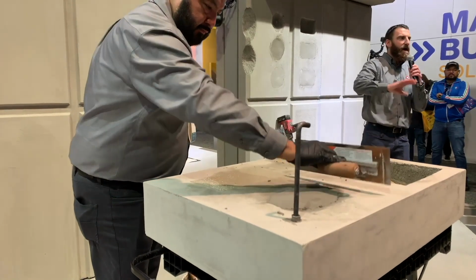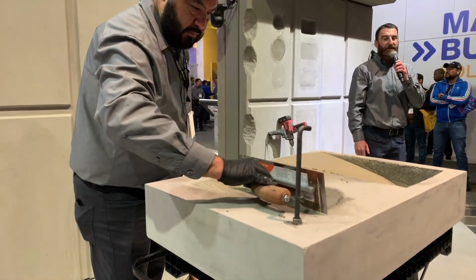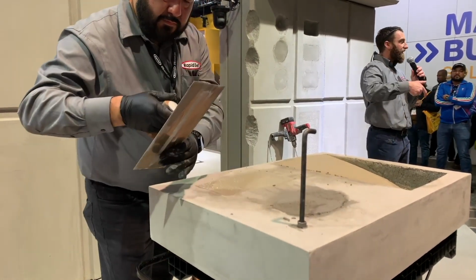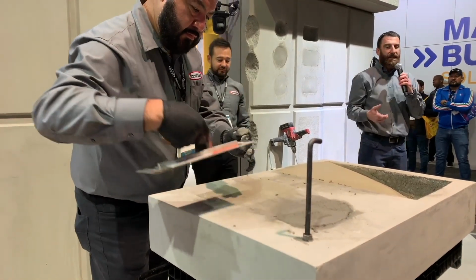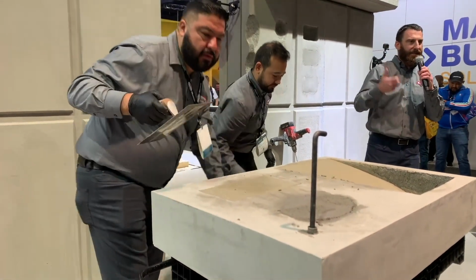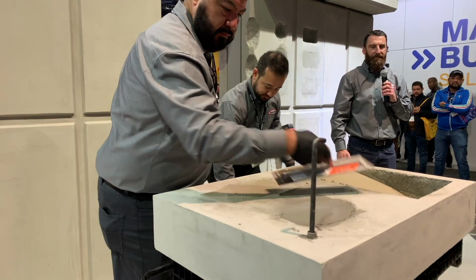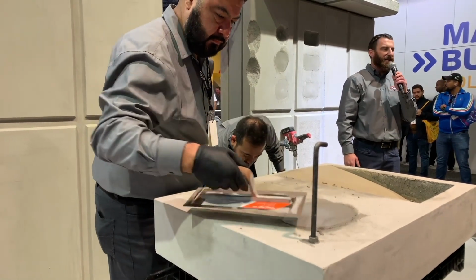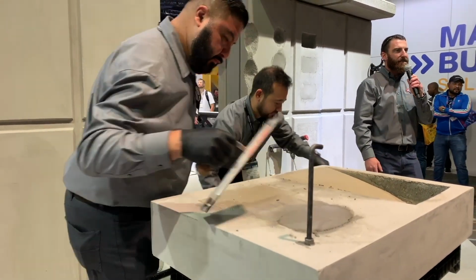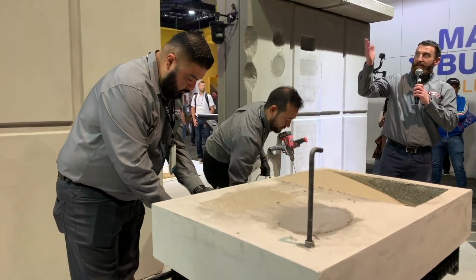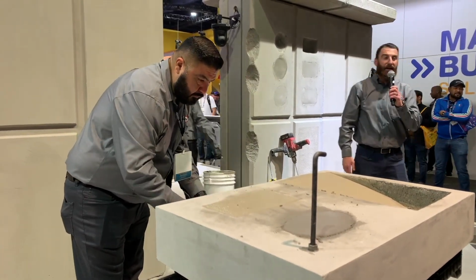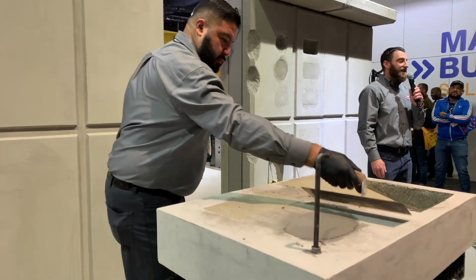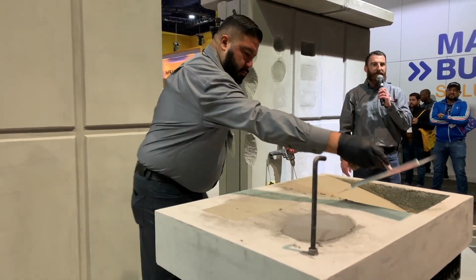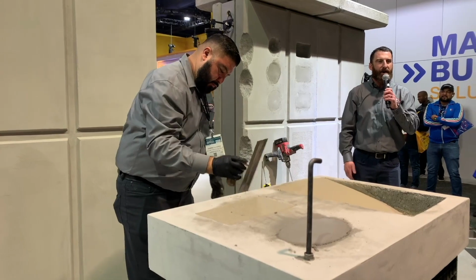So it's used for a wide range of anchoring applications. We've even used it on tilt-ups to anchor the eye bolts when they're lifting the tilt walls. And we know there's no room for error when lifting tilt walls. It also can be applied in temperatures ranging from 14 degrees Fahrenheit up to 104 degrees Fahrenheit. The ultra-fast anchoring has also undergone rigorous testing to be ICC and NSF approved. So that means it can be used with or adjacent to potable drinking water.